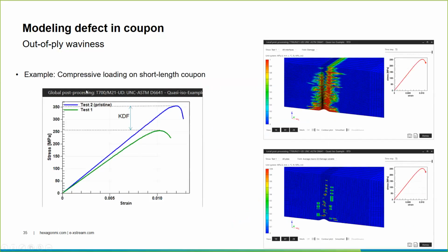So the idea of this development is to run the coupon with and without the defect. Without the defect is the pristine one, and we extract the knockdown factor. Typically here I run a coupon with this defect, and we see quite a severe amplitude of waviness in the coupon. Then we can extract the strength with the defect and the strength without the defect, and we can compute this knockdown factor.